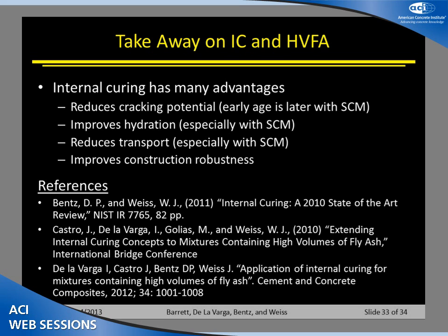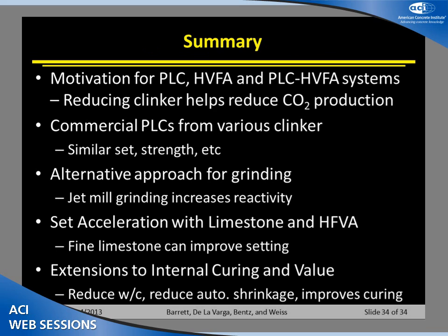One of the other takeaways, and I'll throw this out as sort of a little taster here. It was discussed before, you can have a lot of problems with air entrainers. We've made these high volume fly ash mixtures at a 0.3 water to cement ratio. We put them through freeze thaw testing. Because the water to cement ratio is so low, we don't see freeze thaw damage in those systems. We can't get water into the systems. We can't get them saturated because they're very dense.